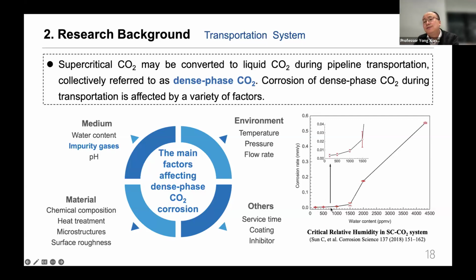Maybe 12 years ago, we also found the same law as this picture shows you. This means that when water content increases above the critical relative humidity, the corrosion rate will increase sharply with the water content. So you have to control the water content in the CO2 pipelines, as well as other impurities. Oxygen enhances the corrosion. SO2 and NOx will enhance the corrosion. We'll talk about it later.